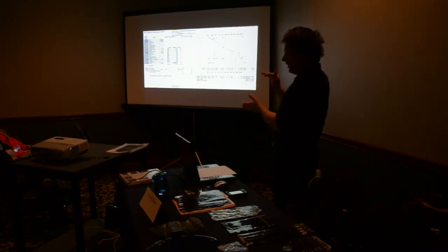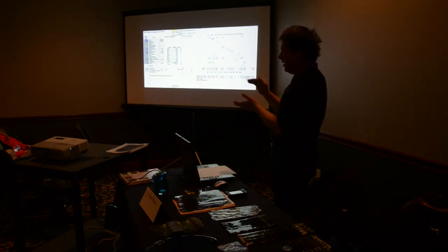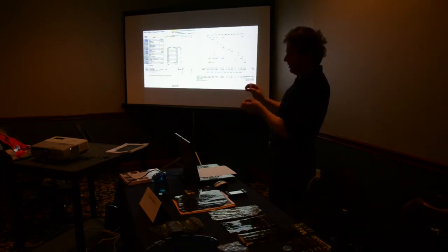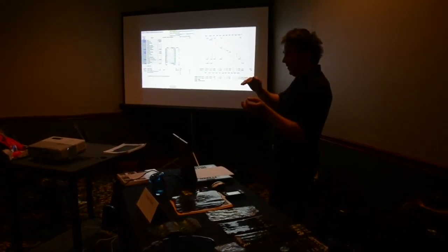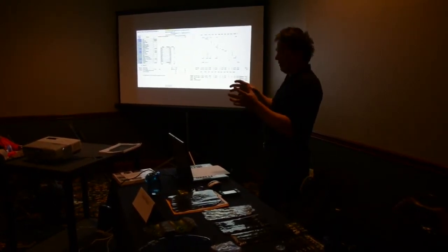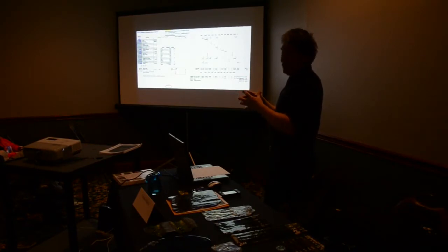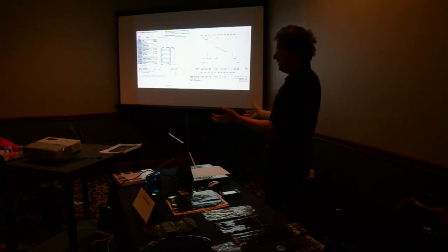You heat it up to working temperature, you have to anneal it for a long time to bring it down to room temperature very slowly. It's a temperature differential between one side of the piece of glass and the other. It'll just crack, especially through the strain phase around 800 to 1000 Fahrenheit. It has to be less than 3 degrees difference between the center and the outside, or it'll crack on you. And below that strain phase, it'll crack if you cool it too fast, but above the strain phase, it'll start incorporating stresses, and it might look okay afterward, and then a year later you go to wash your cup or your plate and it'll crack on you because it didn't properly get annealed through that higher temperature range.